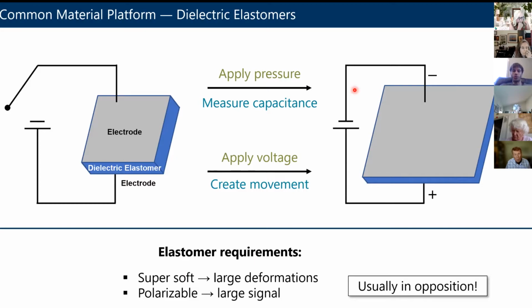When you apply voltage, you want to create an induced charge, or when you apply pressure, you want the material to polarize, which creates a signal that you can measure. And unfortunately, you can't really do both of these well. If you make something really soft, it tends to be non-polarizable with traditional materials. And if you make something polarizable, like for example, nylon is pretty polar, it tends not to be super soft. So these requirements are in opposition.